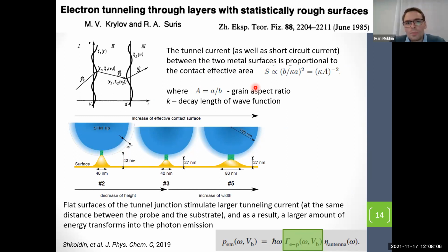So normally thermal evaporation. Is it just standard thermal evaporation? It's very broadly used. It's a very standard approach for metal evaporation, for contact fabrication. It does not require very sophisticated equipment. So that's why we use this approach to evaporate metal. But of course, we can use single crystalline gold with absolutely flat interface. Yes, it's possible to fabricate such kind of structure.